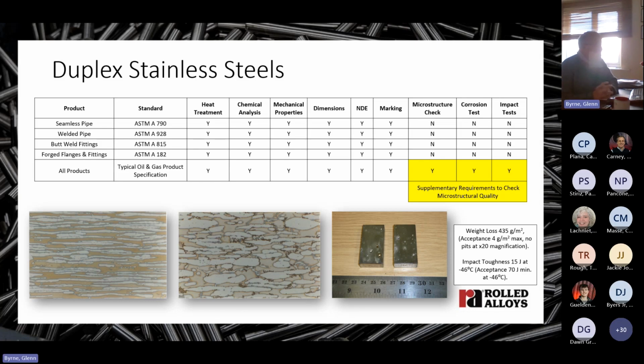Now, sophisticated users have recognised this, and they apply their own supplementary material specifications that are in addition to the requirements of the ASTM product standards. And these detail the methods of testing and acceptance levels that confirm the microstructural quality of the heat treatment batch tested and give confidence that the parts will perform as intended. Now, ASTM A928 or ISO 17781 cover this type of testing.